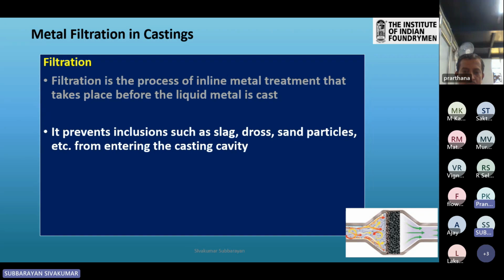So it prevents inclusions such as slag, dross, sand particles, etc. from entering the casting cavity. One catch here: whatever type of filter you use, it broadly filters slag, dross, everything, but the liquid slag which comes from the metal or from the ladle, the filtration effectiveness for liquid slag is not as good compared to filtering other inclusions. Meaning, the cleaner the metal, the more effective the filter is.